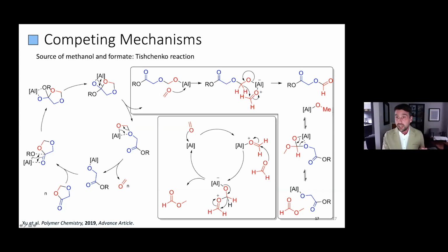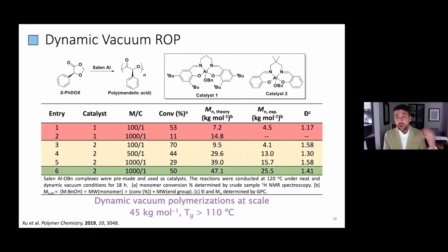Because anytime I have a new chain end, I effectively cut my molecular weight in half. So think of it like this. If I have 100 monomer units, I would have a degree of polymerization of 100 there. But if I have one single Tishchenko reaction happen, my degree of polymerization is now 50. If I have two happen, it's now 25. And that's a real problem in terms of controlling molecular weight in these systems. So how do we solve this?